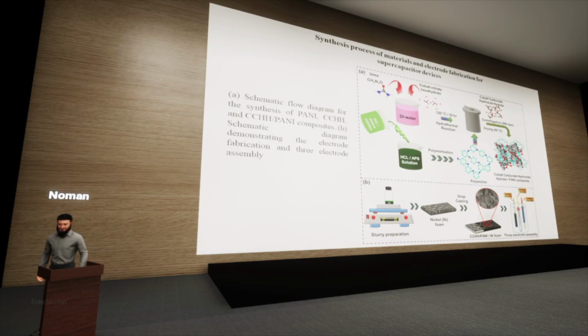After making the nanocomposite, we made the electrode for supercapacitor testing. For the testing, the slurry preparation was carried out on a hot plate, followed by deposition on nickel foam, and then the nickel foam three electrode assembly was used to investigate the electrochemical energy storage performance.